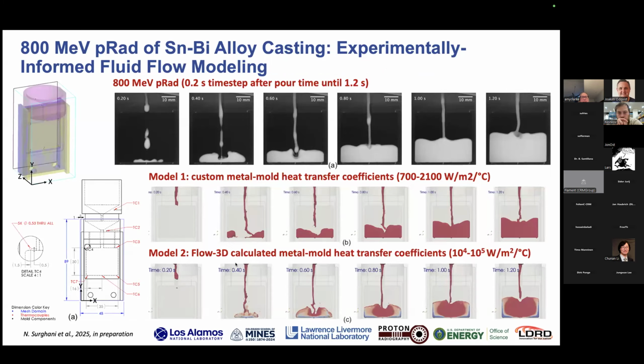So this is a nice example of 800 MeV proton radiography. These are snapshots of metal casting, looking at the casting fill process. Down here is just a little schematic of the graphite mold assembly that we use. And then you can see we're loaded up with thermocouples so we can measure the temperatures and really start doing some comparisons. So one of the things that's always of interest to us, when we're doing the modeling, is are we getting that right?